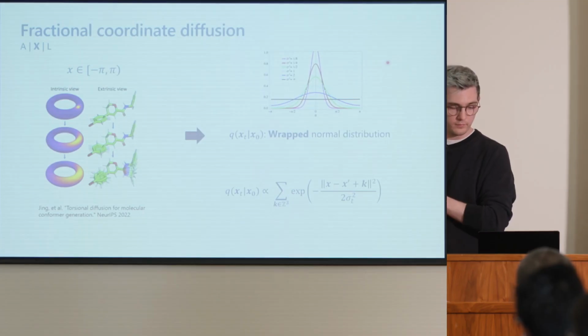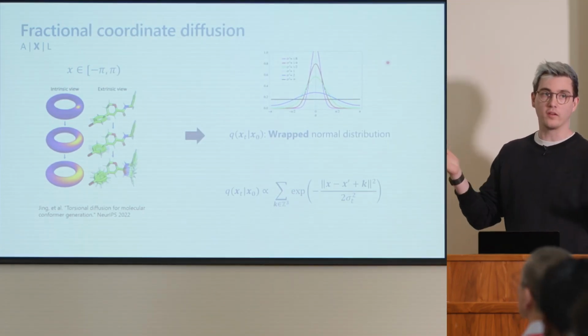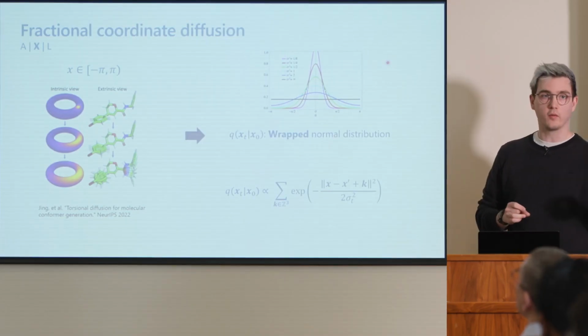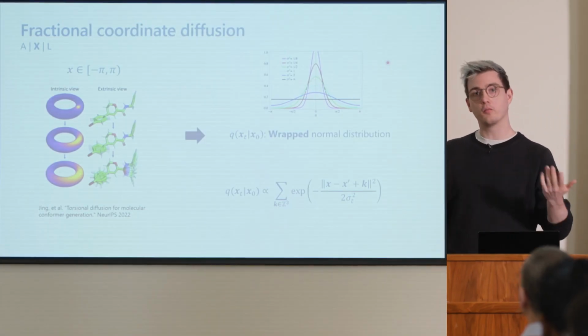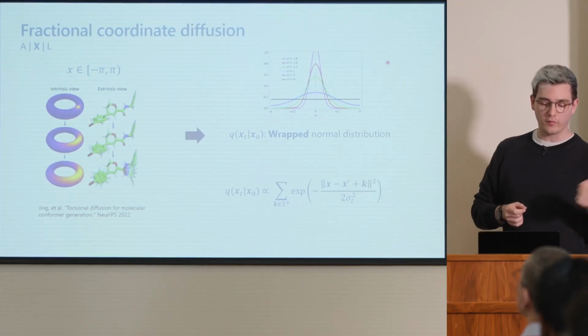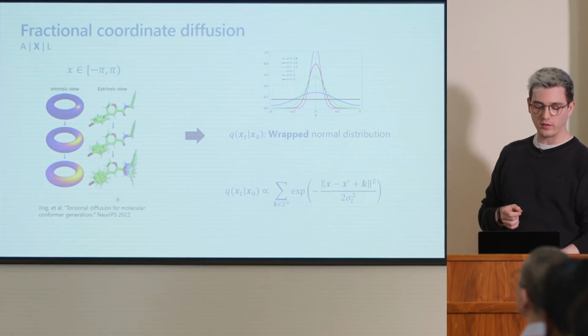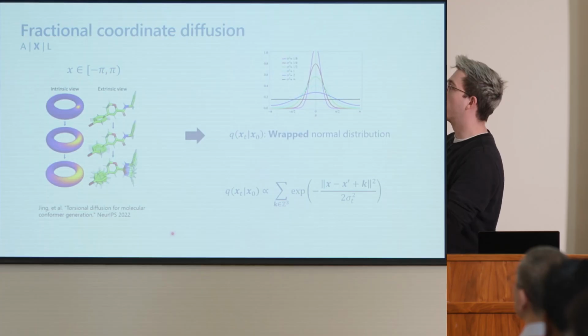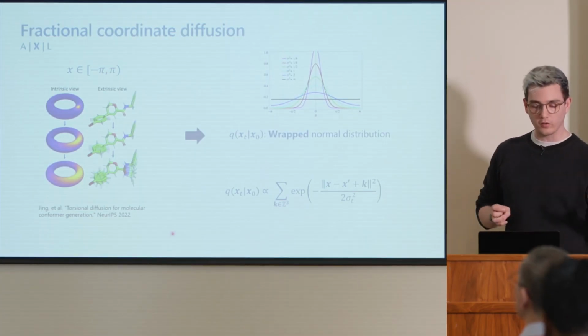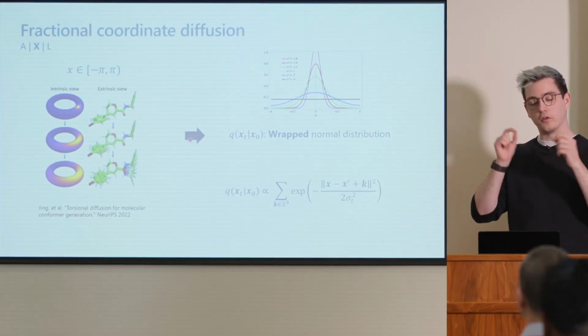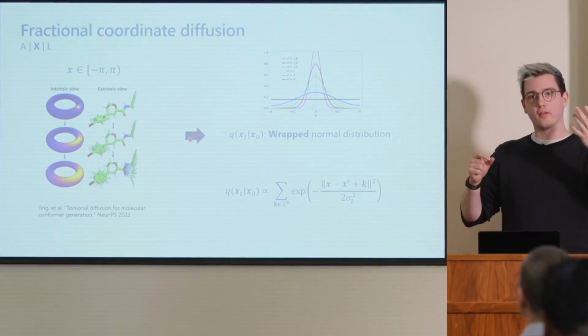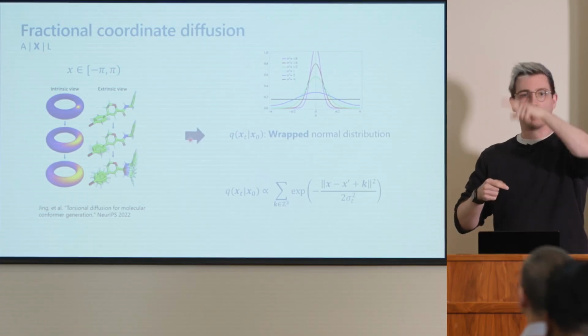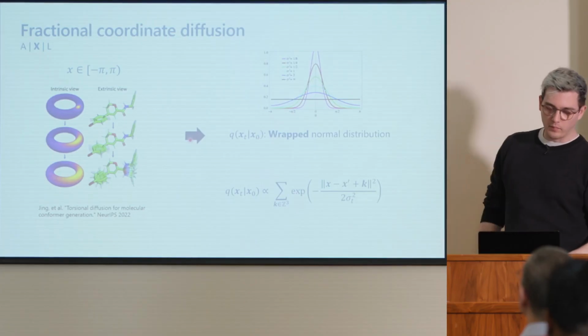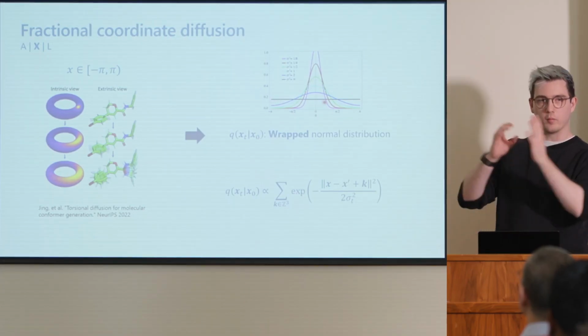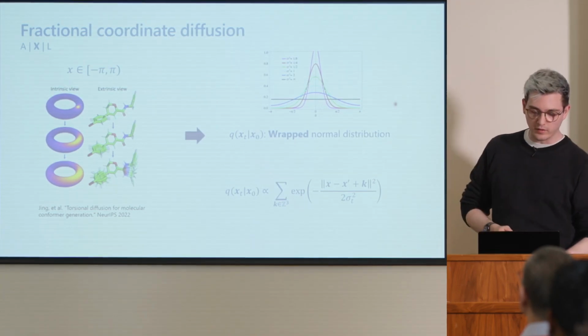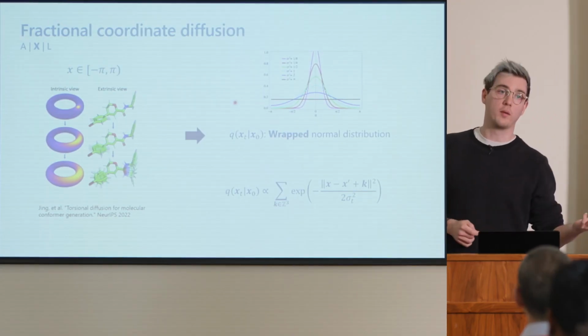For the fractional coordinate diffusion, so the coordinates inside the unit cell, this periodicity that I mentioned implies that we can't just take a standard diffusion process where we just add Gaussian noise and we're done, but we have to be a bit more clever. We use some methodology that they came up with at NeurIPS 2022, where they talk about torsional angles in molecules, and really the principle is the same. We're using a wrapped normal distribution, which you can think of as a normal distribution defined on a circle. You just wrap around whenever you hit the boundary, and that means that if you add more and more noise, so your sigma in the Gaussian increases, finally you'll end up with the uniform distribution that is also easy to sample from, of course.